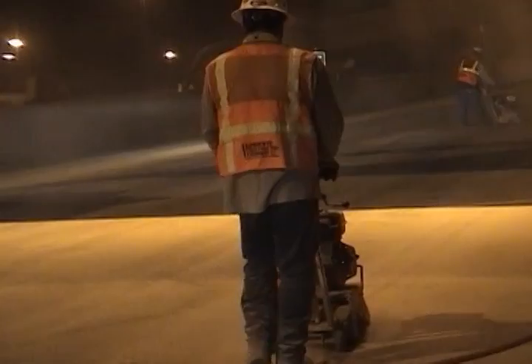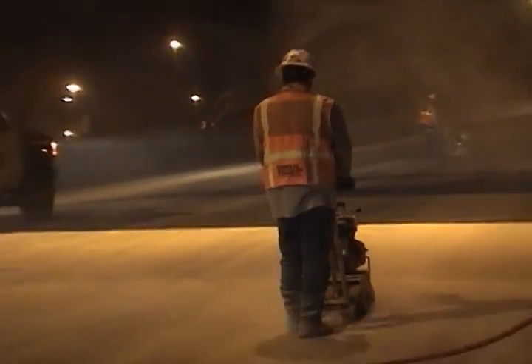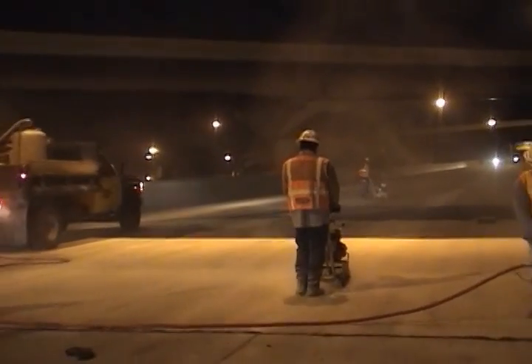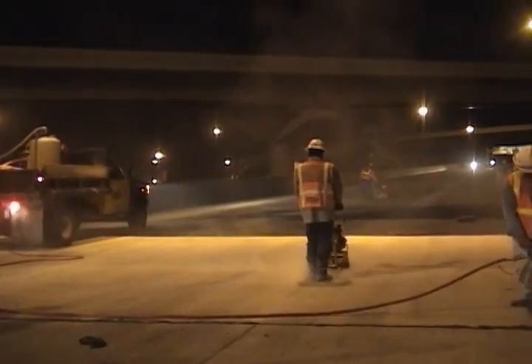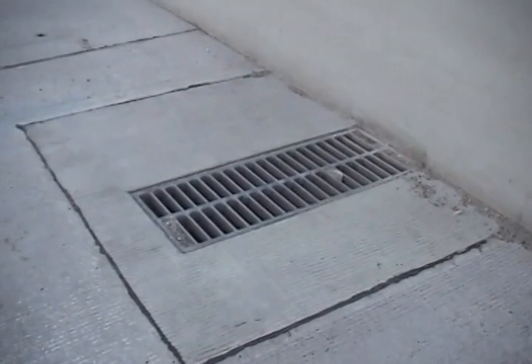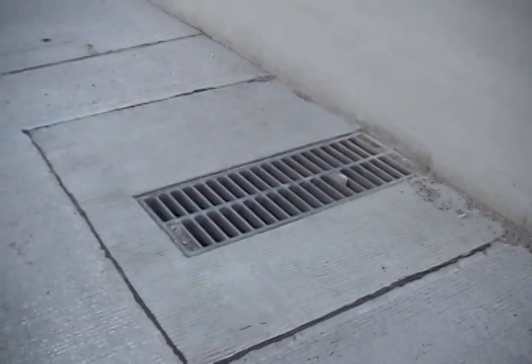Once all the blasting is complete, the deck will be cleaned with a vacuum truck to ensure no sandblasting grit or steel shot is left on the deck. Once the deck is cleaned, the drainage grates and expansion joints must be covered, or they will be filled with epoxy, potentially rendered unusable.